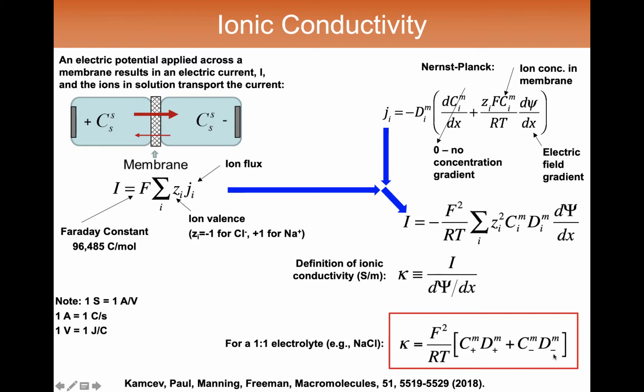Now, remember, for permeability, for concentration-driven permeability, it was the concentration and diffusion coefficient of the rare species, that is the coion, that dictated the permeability coefficient. The situation here is opposite with conductivity. It is the majority species that carries the vast majority of the current.